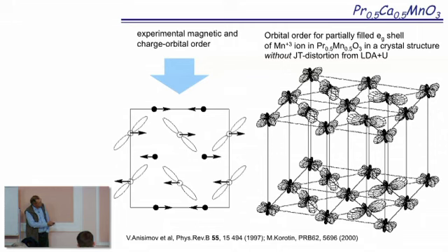You see that size of those orbitals is approximately the same, which means that integral is approximately the same. So this charge order is more like an orbital order. Nevertheless, we could interpret it as a charge order, because all properties will be described pretty well if you suppose that you have charge order. But you should know that just by numbers it is not charge order at all.